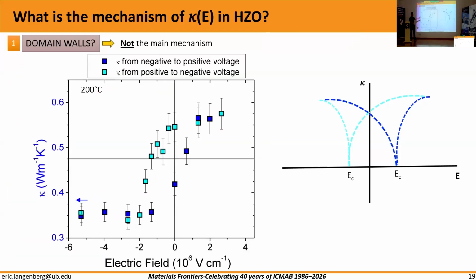Our picture is a hysteresis loop resembling a polarization versus electric field hysteresis loop, and we don't have that picture here. So domain walls may affect the thermal conductivity in our hafnium zirconium oxide, probably, but not sufficiently. Or at least it's not the main driving actor controlling the thermal response of our hafnium zirconium oxide.